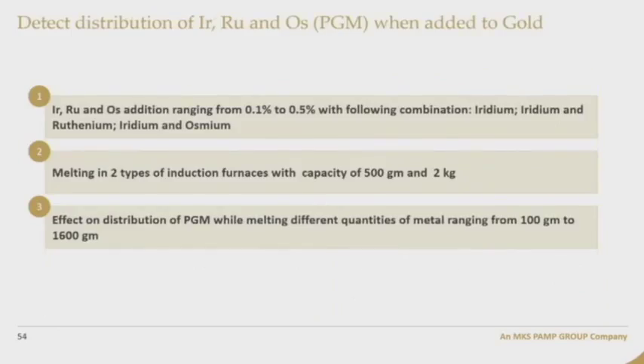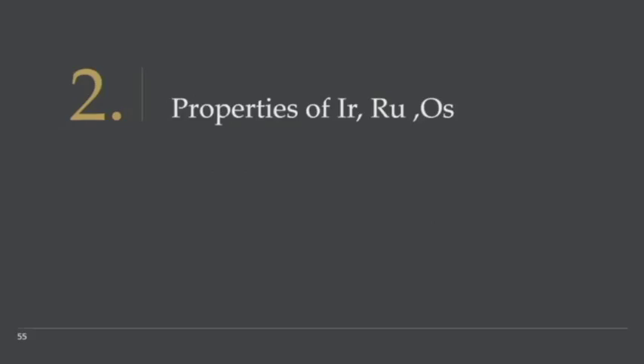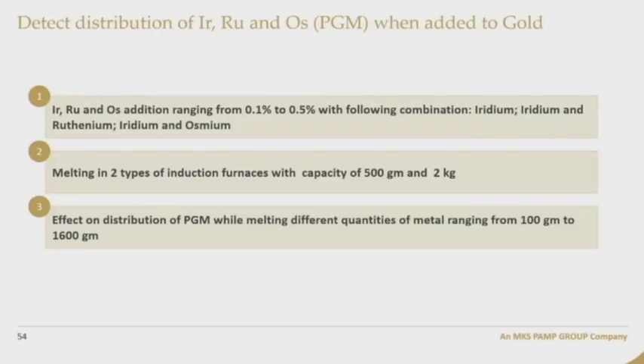So just to tell you what we did, we made 3 alloys with gold: one with iridium, second iridium and ruthenium, and third iridium and osmium, varying the percentage of iridium, ruthenium, or osmium from 0.1 to 0.5%. We also studied the distribution if we melt it in a small 500-gram furnace or a 2 kg furnace, or what is the effect if we melt 100 grams or more than 100 grams, say 1.5 kg. How does the distribution change?